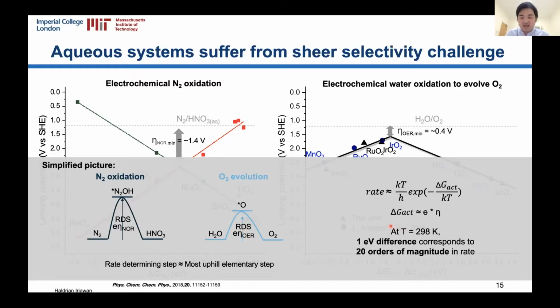And then at room temperature, 1 eV difference actually corresponds to 20 orders of magnitude in rate. So here we can understand that the reason why we're not really detecting any nitrates in our experiments is because at the relevant potentials where nitrogen oxidation can happen, oxygen evolution, the competing reaction, would be happening at the dominant rate.